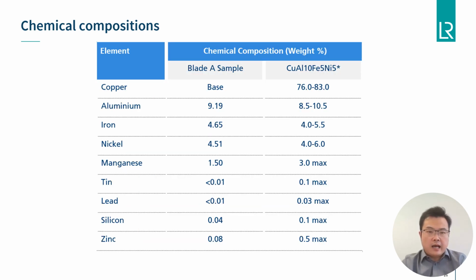As a common practice, we removed a sample from the blade, ensuring there are no weld metals included, and then sent it to an external laboratory for chemical analysis. The chemical analysis results are within the limit for the typical nickel aluminium bronze alloy. It is mainly copper with approximately 10% aluminium, 5% iron and 5% nickel.